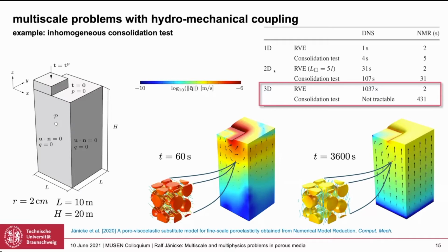Just to give you an idea about the speed up, I brought an example which is more related to geotechnical engineering. It's a consolidation test with some inhomogeneous loading. That's a loading plate here. This body has a length of 10 meters and a height of 20 meters. It consists of material with some hypothetical inclusions, where the inclusions have different material properties. But the important thing is that those inclusions are way smaller. They have a radius of 2 centimeters. If we would resolve this fully in this domain, with a direct numerical simulation, we would need to resolve something like 2 million of those inclusions.